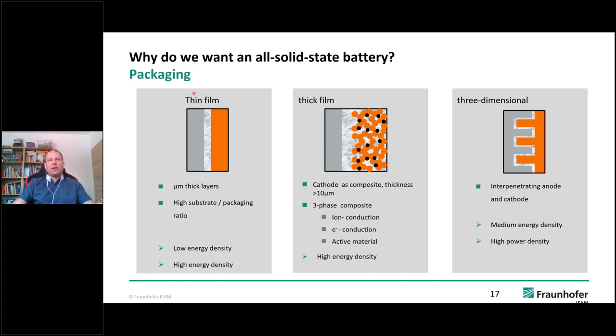On the one hand, we have the thin film battery. This is actually something that you can already buy, which is completely made by evaporation processes. So we have just micrometer thick layers of each anode, cathode, and separator, which are sputtered directly through physical vapor deposition on top of each other, making very nice and very flat appearances, which can be built together to build cells. The problem is that we have a low energy density, but